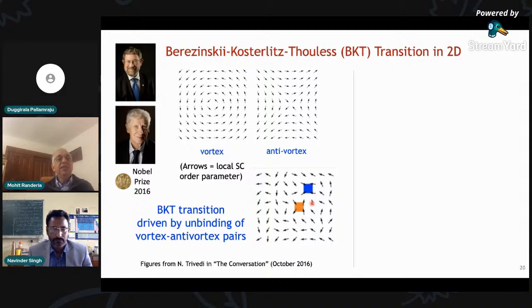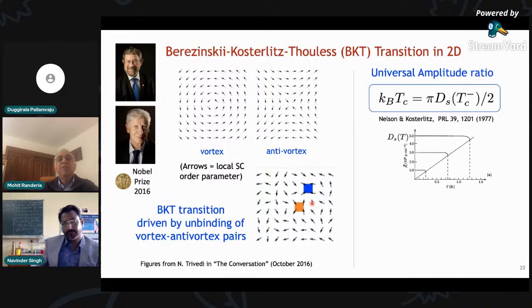But when you hit the BKT transition temperature Tc in 2 dimensions, the vortex-anti-vortex pairs dissociate and completely disorder the sample. And now it's intuitively obvious that since it's the phase disordering which is responsible for this, Tc must be driven by the superfluid density. And there is a very famous result of Nelson and Kosterlitz that Tc is just given by the superfluid stiffness